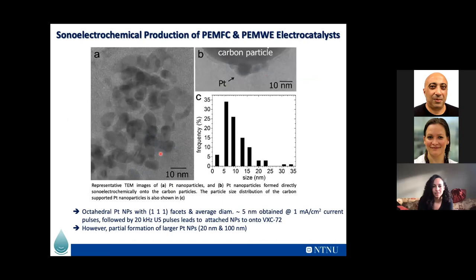What we notice is that, yes, we can get those 5 nanometer nanoparticles, but we also found that after so many minutes of sonication or pulse, you had the detachment of those platinum nanoparticles from the substrate. So don't forget, the bonding between the carbon support and the platinum is quite weak. We also did some ICP-MS work, and we saw a partial formation of larger platinum nanoparticles, so they tend to aggregate and dissolve back into solution.